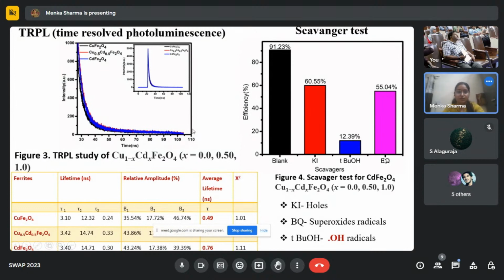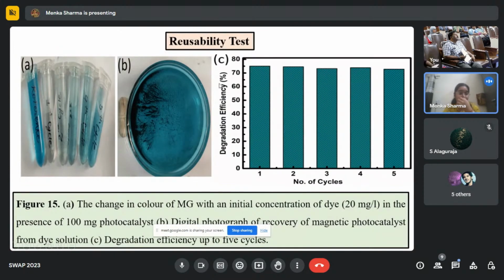these two dyes. We performed the reusability test because the sample is magnetic in nature, so we can reuse and recover the sample after the reaction is over. We have performed the reusability test up to 5 cycles, and there is only a slight decrease in the degradation efficiency up to 5 cycles. So we can say that the photocatalyst can be reused and recovered after the reaction is over.